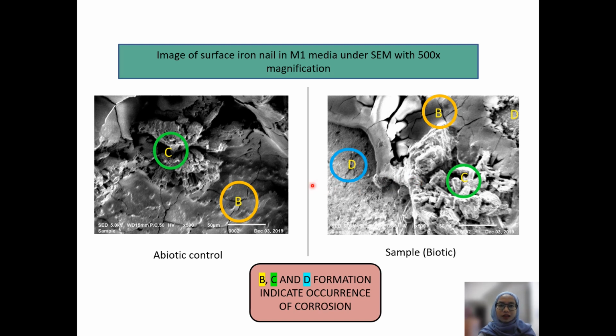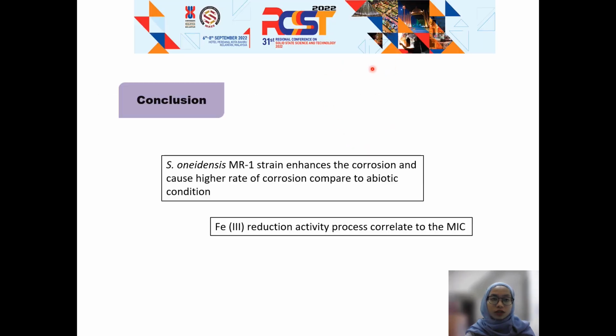Technically, as the ferric iron is reduced to ferrous, the insoluble ferric changes its state into soluble ferrous. So the soluble form of ferrous aids the pitting process, causing the iron nail surface to be cracked. As a conclusion, this research suggests that Shewanella oneidensis MR-1 enhances the corrosion process by the formation of corrosion product on the iron nail surface.